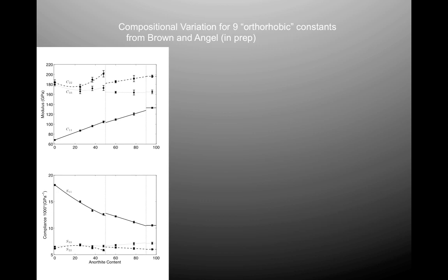And as you look at this, you'll notice that as a function of composition, some elastic constants proceed from albite to anorthite with very little change from the C bar 1 to the I bar 1 structure, whereas other elastic constants show some appearance of discontinuity. And in a detailed examination of the structure, we can show that, in fact, the constants that have discontinuities are the ones you would expect for the nature of the difference in the structure between C bar 1 and I bar 1.